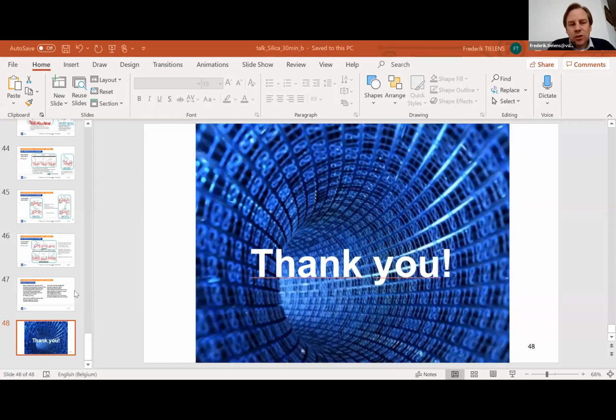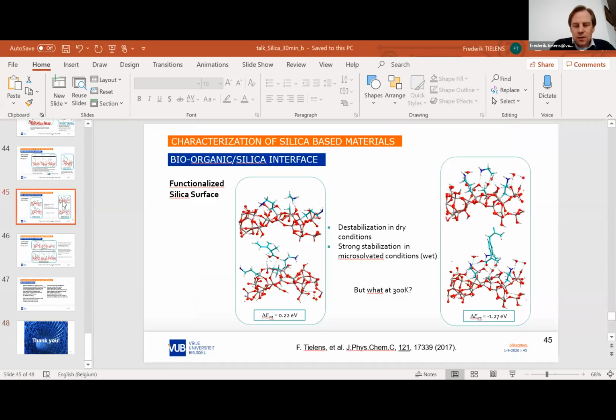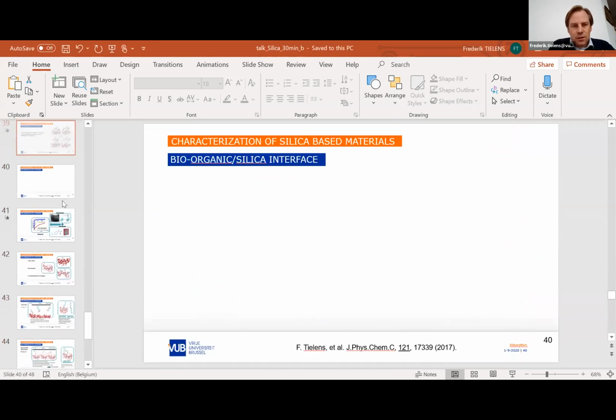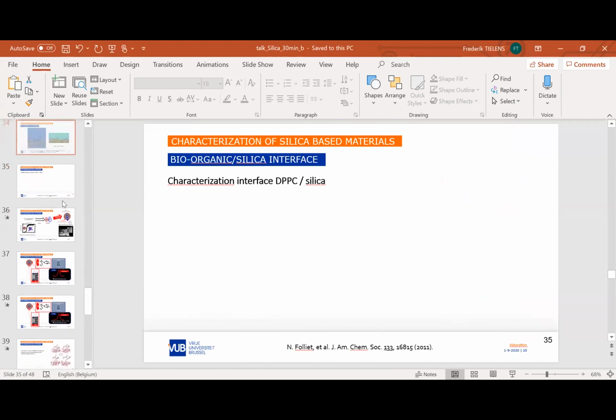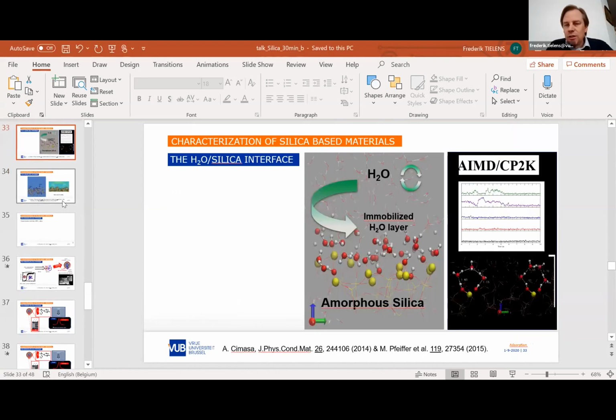Normally we don't use clusters. Maybe I can go to the slide you mean. All calculations were done with CP2K or VASP, so we don't use clusters. When you see a cluster, it's because maybe I have not shown the periodicity. So we are talking about periodic structures, but not about clusters. No, indeed, I have not written any cluster.